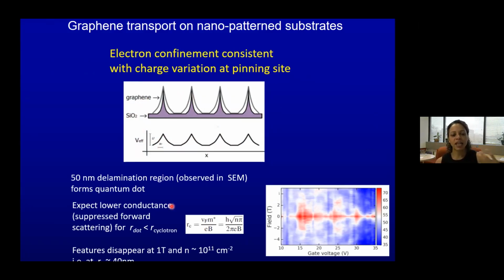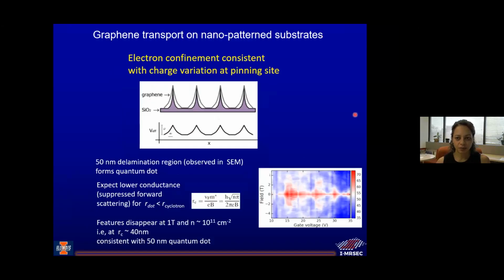When we compare the length scales of dots plus our confinement regions, we can see that we have confinement on a scale of about 40 nanometers electronically, which is consistent with the approximate size of the dots that we see in these devices. Okay. So this kind of confinement behavior that we see is consistent with confinement due to pinning regions of the graphene. Okay, so that's one thing.